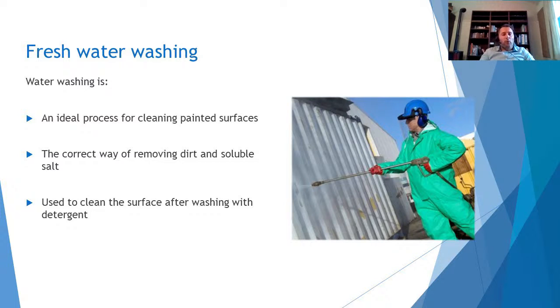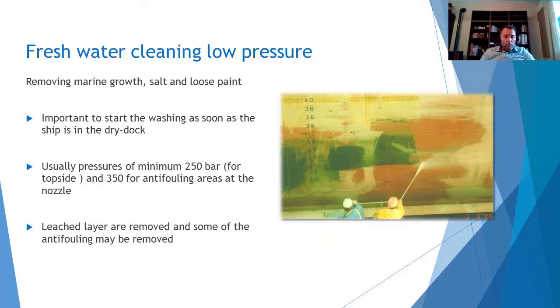This is an example of fresh water cleaning, low pressure, used in shipyards. In shipyards, water is used to remove coating, for example a leached layer or antifouling coating. It's important to understand that water is used not only to pre-clean the surface, but also to remove some particular coating or material that is not tightly bonded to the substrate.